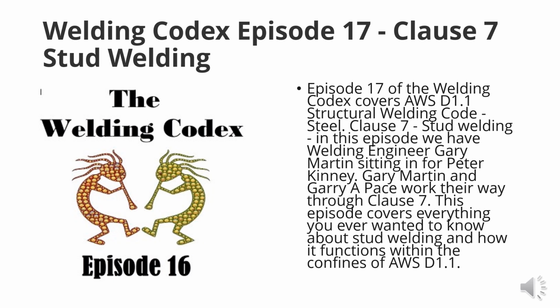Stud base qualified with an approved grade of ASTM A29 steel and meets the standard mechanical properties shall constitute qualification for all other approved grades of ASTM A29 steel, provided that the conformance with all other provisions stated herein shall be achieved. 7.9.4, duration of qualification. The size of stud base with arc shield, once qualified, shall be considered qualified until the stud manufacturer makes any change in the stud base geometry, material, flux, or arc shield which affects the welding characteristics. So they're essentially qualified for the life of that design. And then we move on to preparation of specimens. So again, this is all under the 7.9 manufacturer's qualification.